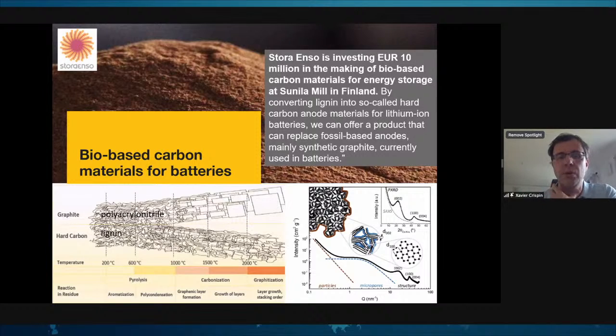So in that case, instead of using polyacrylonitrile, which is typically the synthetic polymer used to form graphite, we can use lignin to form hard carbon. Hard carbon is not going to be composed of nice graphitic planes of high electrical conductivity. No, it's not going to be that nice. However, it's super cheap and it can be decently good as an electrode in lithium and sodium ion batteries.